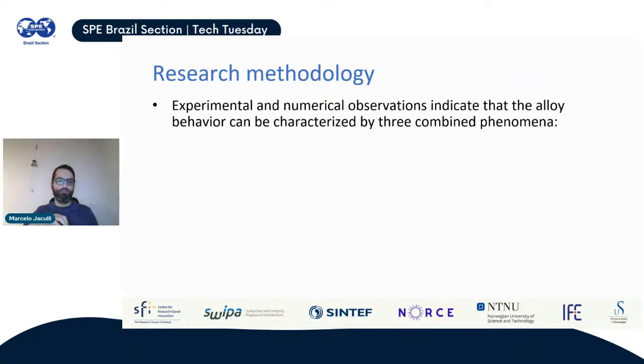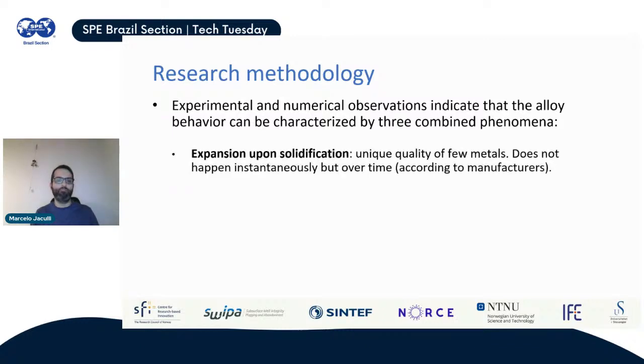Yeah, and I think that's basically the main goal of our numerical model: what we can provide in terms of characterization of this alloy. Based on our experimental and numerical observations, we realized that this particular problem is very unique in terms of the characteristics of this alloy, and it can be characterized by these three combined phenomena. The first one is the expansion upon solidification that I talked about so far. It's a very unique quality of this alloy, and it's its main selling point, basically. But one very important thing that manufacturers claim is that this expansion doesn't happen instantaneously when the phase changes. After the liquid alloy becomes solid, it's not going to expand completely, but it's going to expand over time. So you are expected to have some improvement over time.